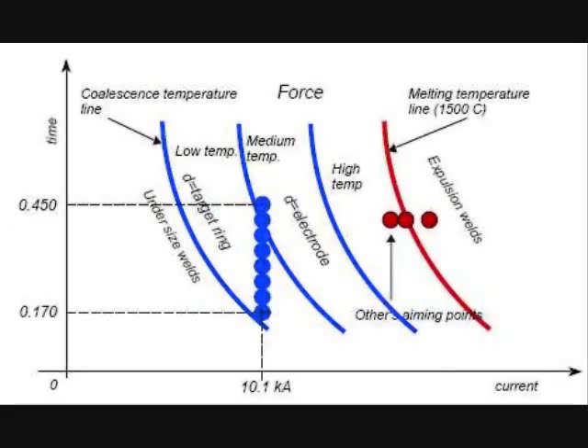In this slide, I chose the first 10 coupons' data to plot on this weld lobe. You can see the whole thing divided into 3 parts. The 0.450 is the last one that fell right on the line between the low temperature and medium temperature range.